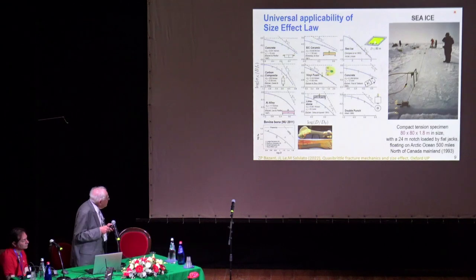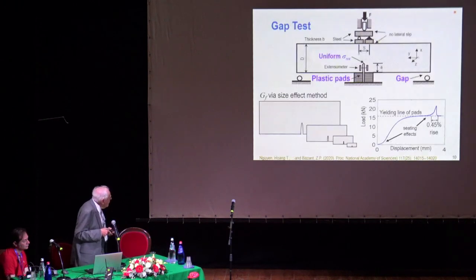Perhaps the most interesting is the test we did, Dempsey and I, 500 miles north of the Canada mainland on the Arctic Ocean, where we fractured specimens up to 80 by 80 meters. This is the opposite side. This is one side of the specimen, square like this, expanded at the notch by a flat jack. And it agreed with linear fracture mechanics for sizes bigger than this 80 meters, actually. Linear fracture mechanics in sea ice in horizontal fracture is reached at sizes of about 30 meters. In other problems, of course, we deal with micrometers, so it's an enormous range of scales.